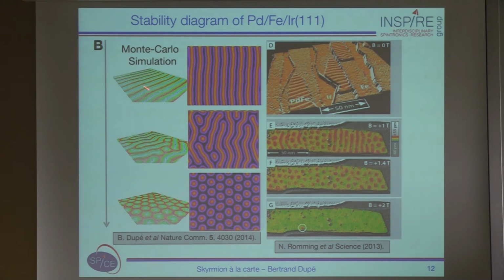So here you have indeed a spin spiral ground state, as I showed you before. You increase the magnetic field. You see that you have this kind of mixed state where you have these stripes here, which are elongated skyrmions or shortened spin spirals. And you have these small round objects here, which are actually skyrmions. And they are skyrmions within the spin spiral. You keep increasing, and you have a hexagonal lattice of skyrmions. So that is very nice.